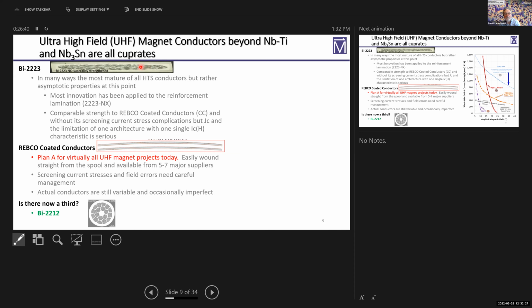It becomes more difficult to screen local charges and things like that. And so you end up with a situation where you have grains, crystals of very good superconductivity, but they are separated from each other by, of course, grain boundaries, which form a totally interconnected network where the coupling is either very bad if it's a very high angle grain boundary, or at a moderately misoriented grain boundary, there is a superconducting coupling, but it's weakened.